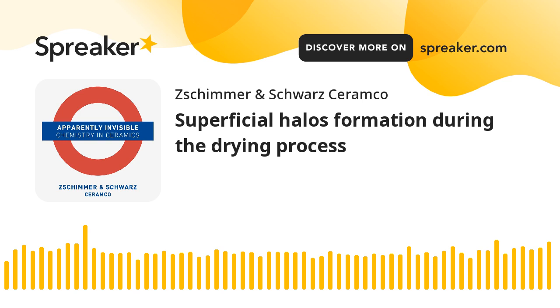As we know, the ceramic mixture after the atomization process undergoes very high pressure during the forming phase, which can be higher than 400 kilos per square centimeter, to produce the raw ceramic body. The raw tile, even after the pressing phase, still contains a water amount that we could define as residual humidity, around 5-7%. The presence of water is essential to provide the clay with the proper plasticity level that is required to model the raw tile under the presses.